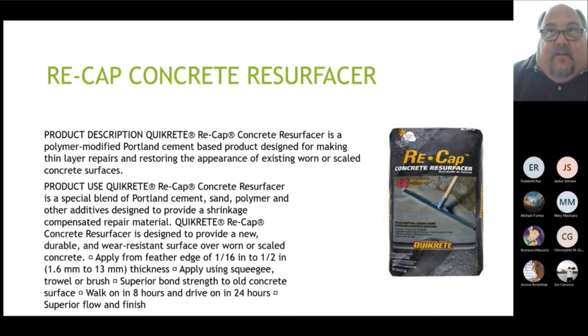And it's really important you retain your control joints and your expansion joints. You can tape the joints off. You're going to want to work with one pad at a time, because this product sets off in about 20 minutes. You don't want to get a big section going, so you can tape off and mask off with plastic around the pad you're doing. Tape off or put a wooden dowel in the expansion joint so you don't fill those joints, because it's just going to crack.